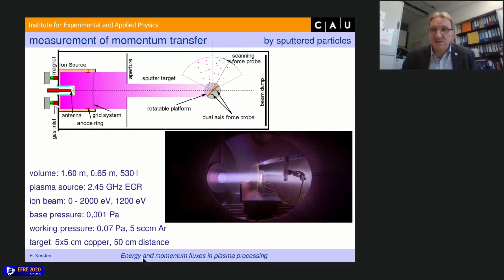Okay, and this is the last slide, I guess, or almost. Then we still go a step further. With this experiment, we measured the sputtering at the target. And now we measure not only the sputtering here at the target, but we measure the deposition of the sputtered particles from the target to the substrate. Now our scanning force probe is the substrate. It is not the target as before. Now it is the substrate.